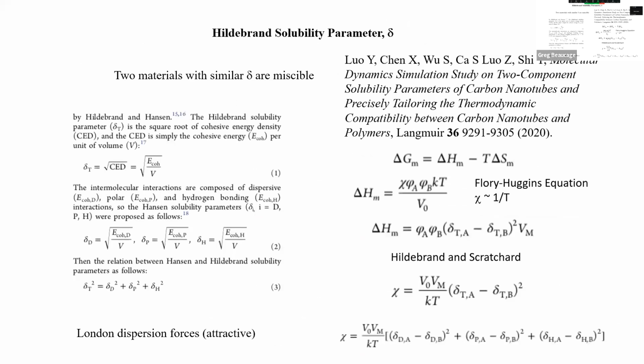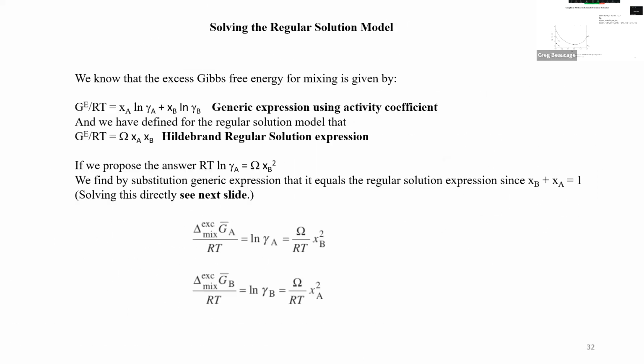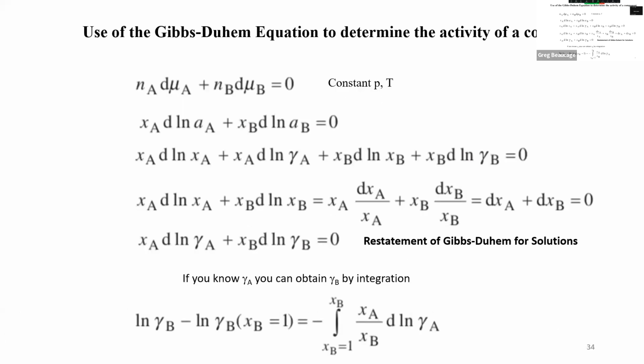So this is one case where this weird Gibbs-Duhem thing that seems to not be of any value has some value. Gibbs-Duhem says that at constant P and T, normally you'd have the chemical potential times the derivative of the moles. In the Gibbs-Duhem, you have the number of moles and the derivative of the chemical potential, and the sum of the two in a binary mixture is 0. And then the chemical potential is log of the activity. Well, activity is mole fraction times gamma, so you can break that into ln of that plus ln of that.